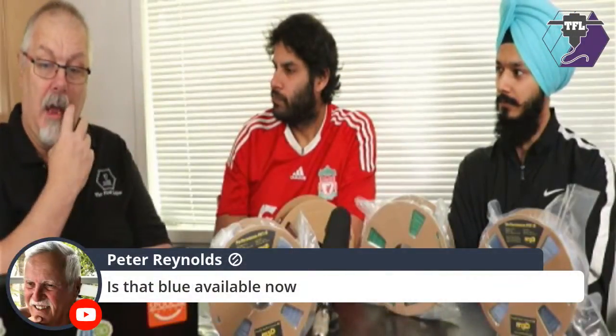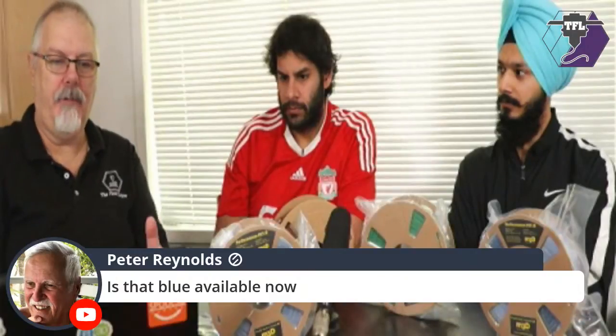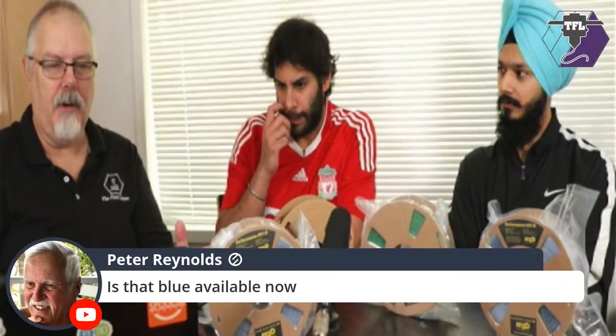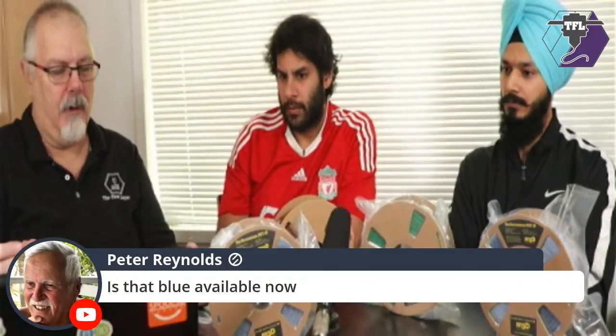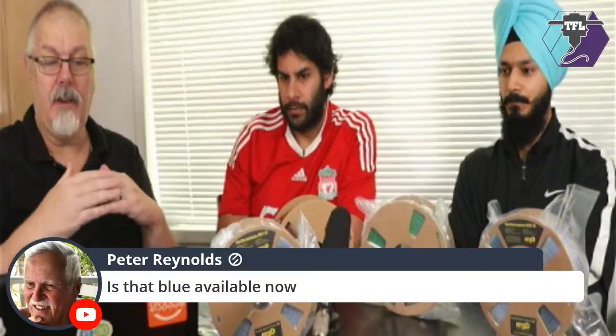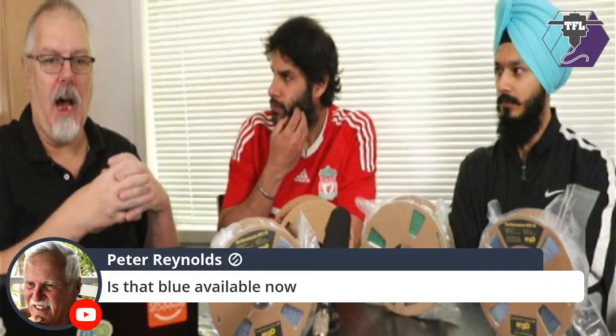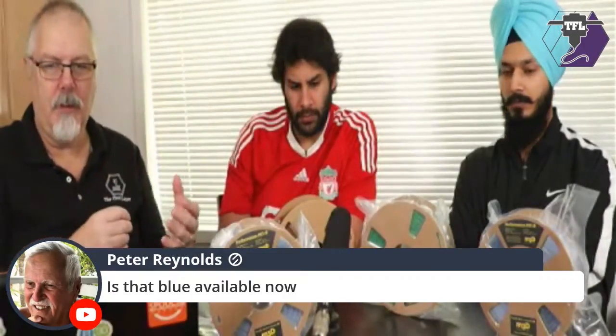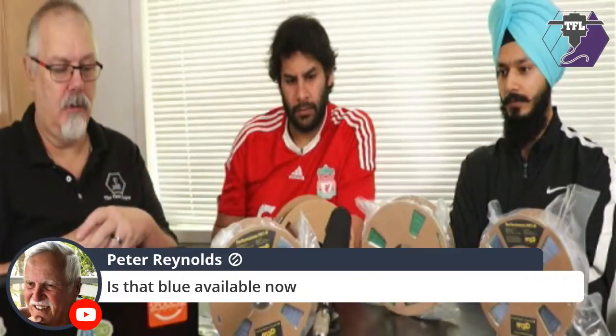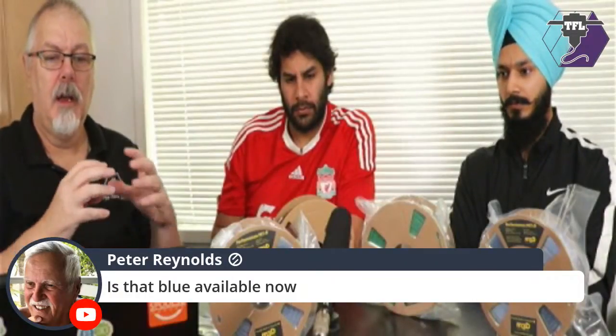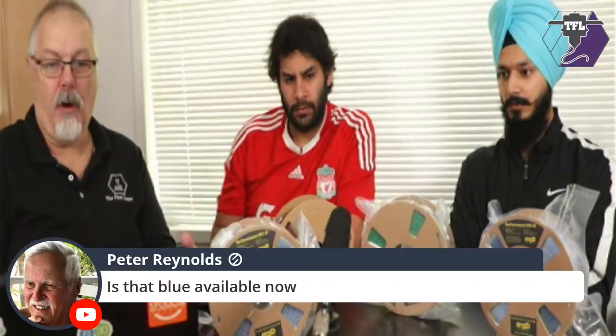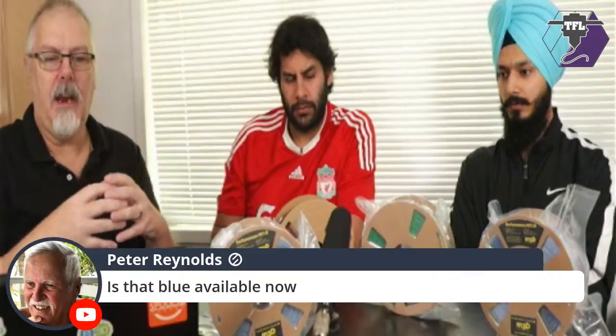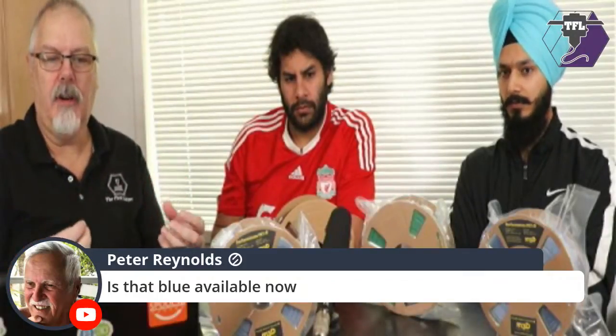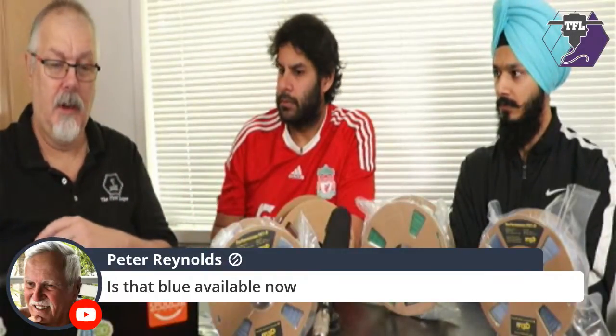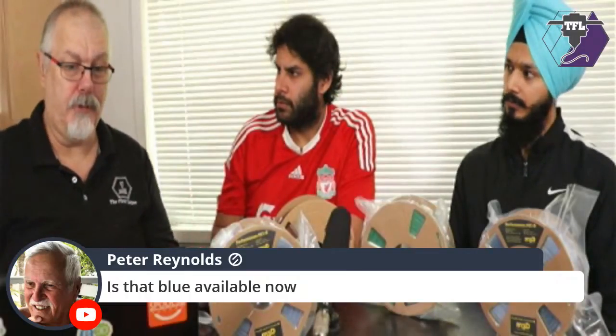I agree 100%. And I think that with Matter 3D, we finally found a material that we can all use. Yes, you got to print it a little hotter, but that's because of the way that it's manufactured, because it uses such a high concentration of raw material, as opposed to some of the other companies out there. And I'm not going to name names because, you know, we don't slam anybody on this show, but some of the lower priced filaments on the market have additives, have fillers. So you're not getting that genuine pure resin material. You're getting something that may have some bits from something that's been recycled, or may have some bits from something that's already been processed and been sitting on the floor for 6 months.